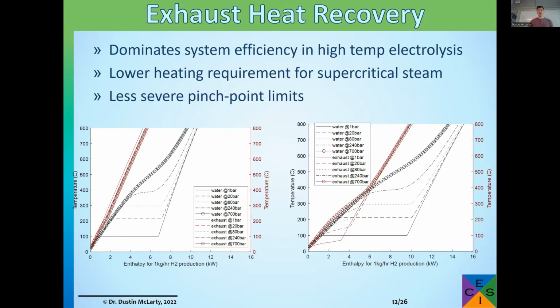The other thing I wanted to point out is when you have more and more humidity in your exhaust system, that's extra water you supply to the system that you didn't split and is coming out of the system, and you're trying to recover that energy. When you have a substantial portion of exhaust humidity, you really run into this pinch point where these lines cross, and that doesn't work in a heat exchanger, because you always need your hot fluid to be hotter than your cold fluid. The heat won't go the other way.